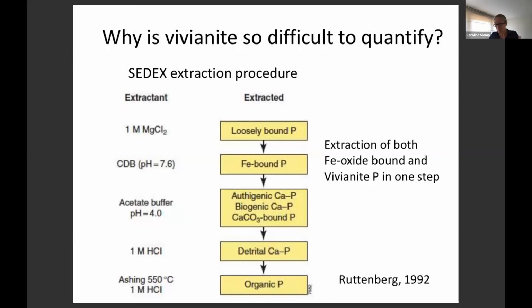And that step targets both iron oxide-bound phosphorus and Vivianite. So they're combined in one step. And so usually when people extract this iron-bound phosphorus, they say, oh, it's all iron oxide-bound phosphorus. But the case I want to make here is that in some cases, it might be almost completely Vivianite.